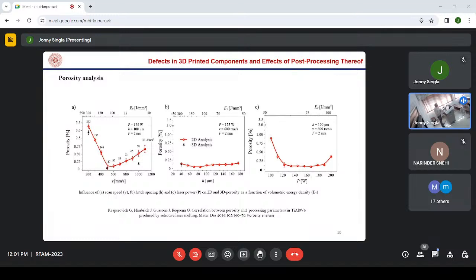And in literature, it has been found that if you keep these four parameters in this range, then porosity will be minimum, because porosity is the biggest problem in additively manufactured components. And if there is porosity, of course, that will lead to poor mechanical properties. Because wherever there is porosity in the material, there is a large possibility of initiation of cracks. And that initiation of cracks will lead to failure of the components. So it is necessary that porosity should be minimum.